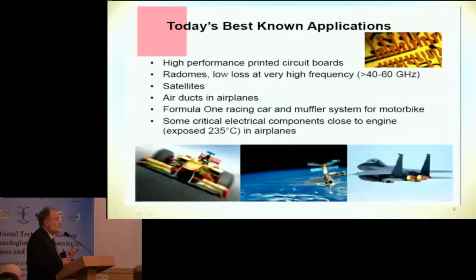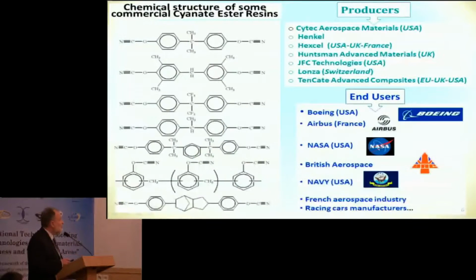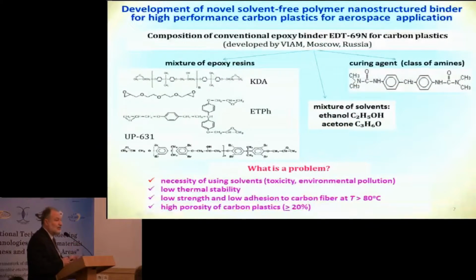So this work was done in the frame of the project and this nanotechnology and nanomaterials program, and we developed the novel solvent-free polymer nanostructured binder for high-performance carbon plastics for aerospace applications. So what was done? We made several developments, and most of them were done on the base of a very promising thermosetting material, cyanate ester resins, and different dispersed inorganic nanoparticles. As nanofillers, we used multi-walled carbon nanotubes, epoxy functionalized polyhedral oligomeric silsesquioxanes with nanoparticle size 1-3 nanometers, and also functionalized montmorillonite.